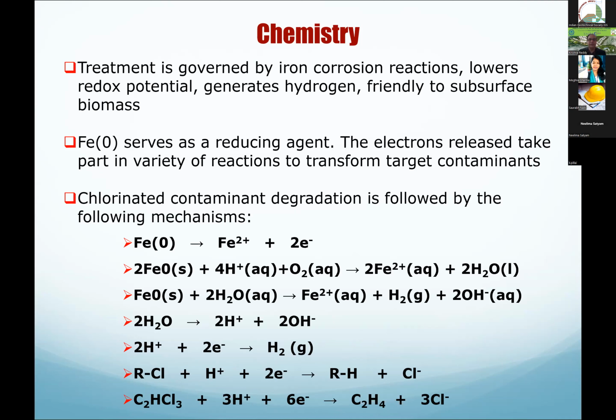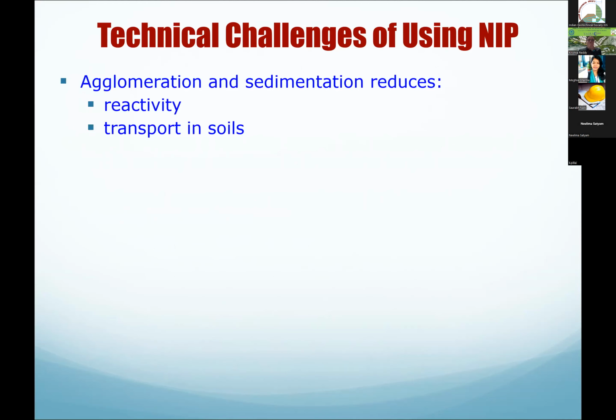Nanoscale iron is used mainly for chlorinated contamination. Chlorinated contamination, basically organics that have chlorine in them, are highly carcinogenic, highly toxic, and they don't degrade easily. So what we are trying to do with these iron particles is dechlorinate them. The chlorine will come out, and the chlorinated organic compound will become hydrocarbons. And if it becomes hydrocarbon, microbes can easily biodegrade it. So it's kind of achieving the risk-based levels, or reducing the risk, by first dechlorinating the contamination, and then following that with bioremediation. So this introduction of the nanoiron particles will dechlorinate the chlorinated compounds. That sounds good, right?